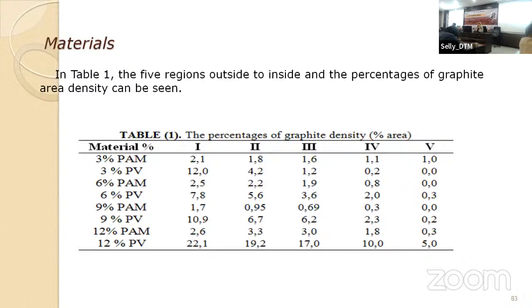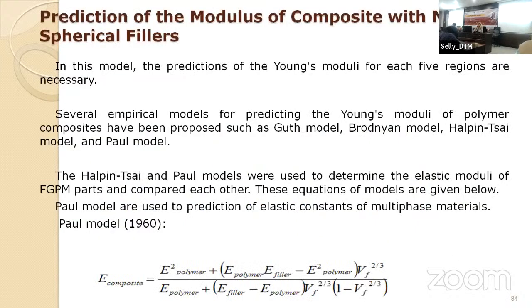Okay, we observed the material and we wrote the table in the 5 regions from outside to inside. For the percentage of the graphite, their density can be seen. And then its model. The prediction of the Young's modulus in the 5 regions is necessary. So we have several empirical models for the Young's modulus of polymer composites. One of them is the Guth model, one of them is the Brodnyan model, the other ones are the Halpin-Tsai and Paul models. Look at that, the Halpin-Tsai and the Paul models were used to determine the elastic modulus of our experimental FGM parts, and we will compare them with each other.